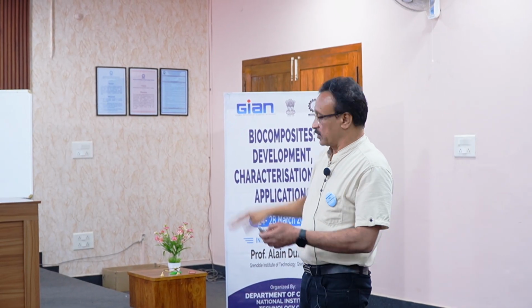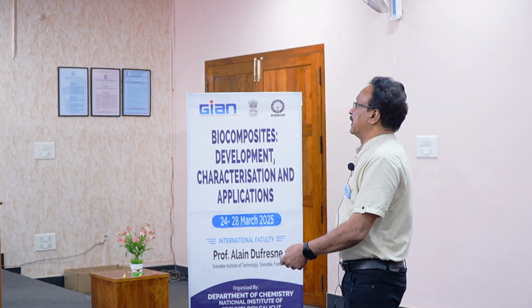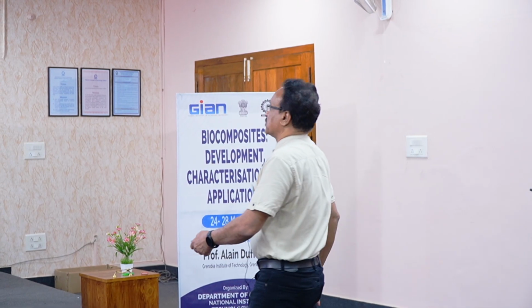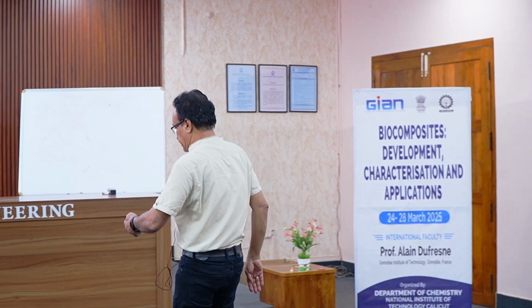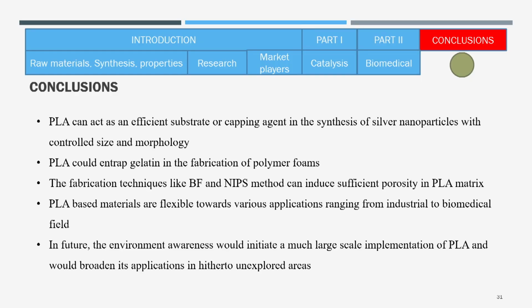What I said is shown as a picture on the right hand side, and that forms, I think, the conclusion. The conclusion from these two observations gave us the confidence that PLA can act as an efficient substrate for catalytic activity and bio drug release, and as a capping agent for synthesis of silver nanoparticles with controlled size and morphology. And the second work shows that PLA could entrap gelatin in the fabrication of polymer foams.